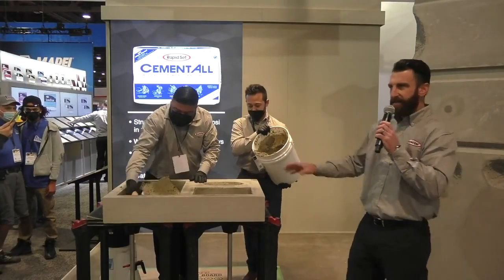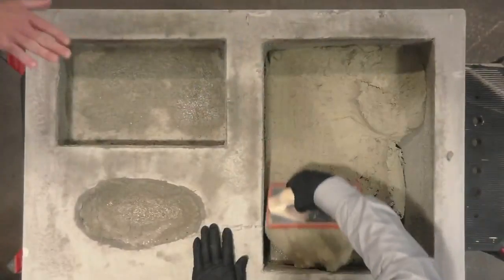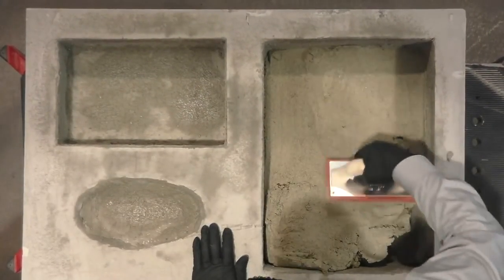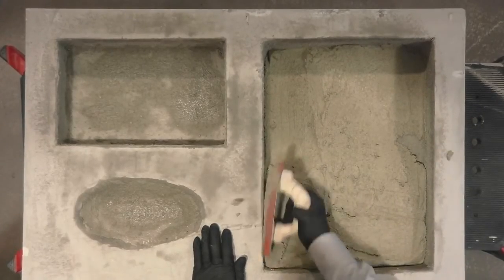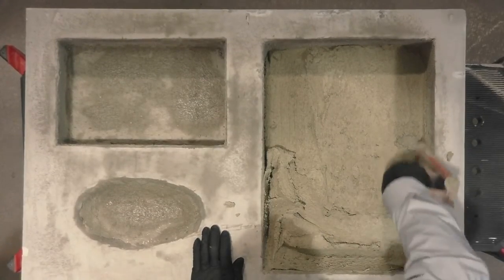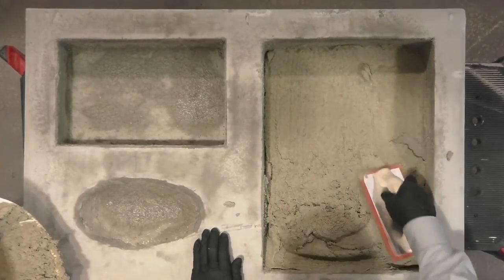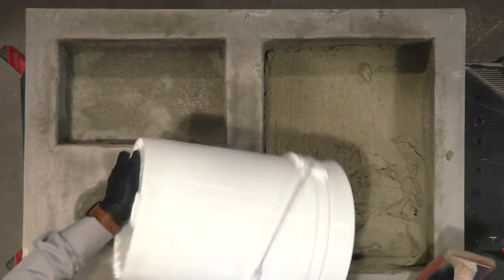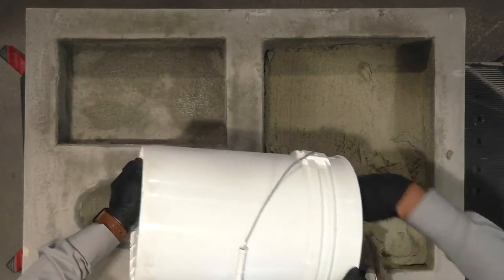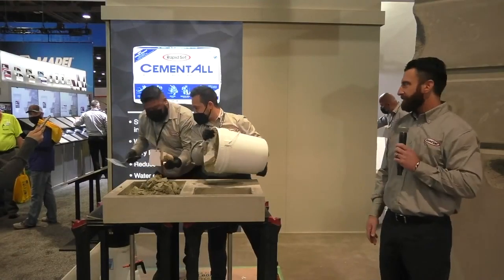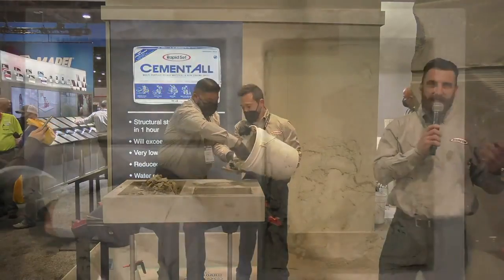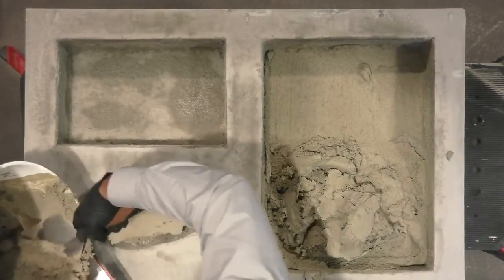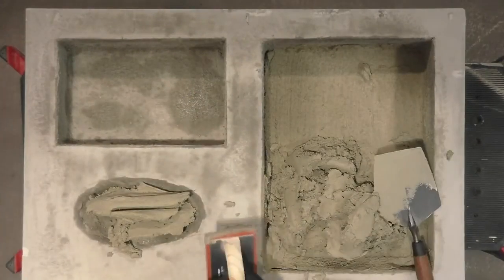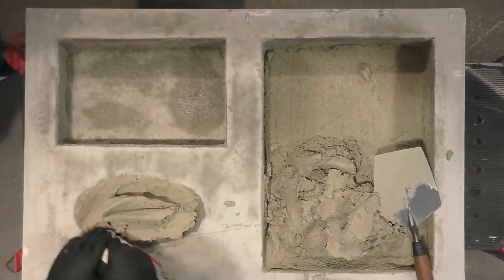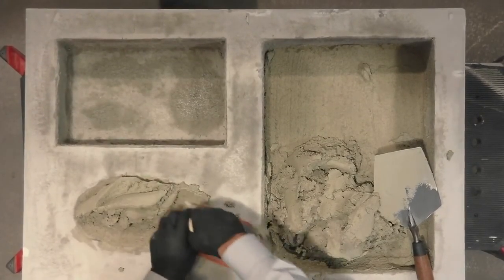So again, here in this demonstration, we'll be ramping it, so it'll go from feather edge up to about 4 inches thick. It has a very low shrinkage, so even when you apply it thick, it has a lower risk of cracking than traditional Portland cement products. You've got about 15 minutes working time on this. It's very fast, and this will gain structural strength of 3,000 PSI in just 1 hour. It'll also get long-term strength. It will exceed 9,000 PSI in 28 days. In this demonstration, we're also showing a spall repair.